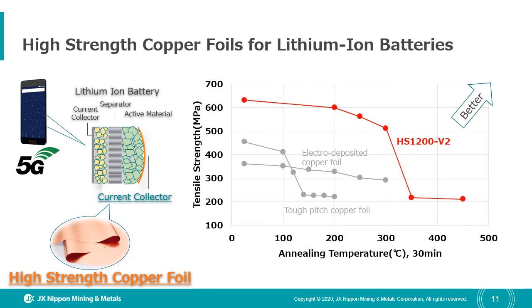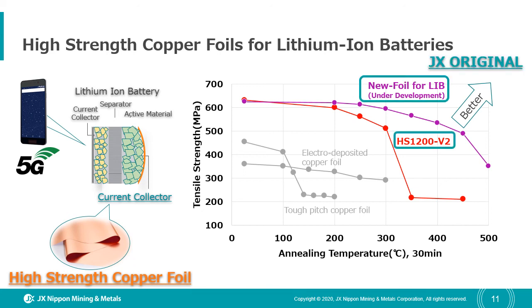JX HS1200V2 original copper foil has greater strength than such conventional copper foils, even at higher temperatures. Lithium-ion battery processing sometimes requires higher temperature treatment. In such cases, we also have a solution in the form of our newly developed foil for lithium-ion batteries. JX high-strength copper foil is supporting a new generation of lithium-ion battery development.